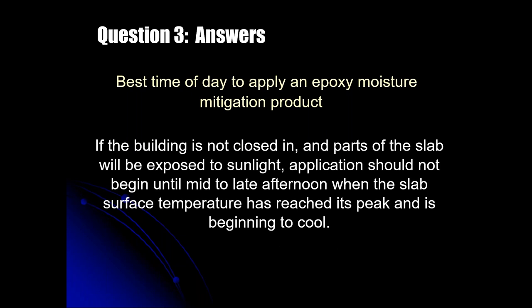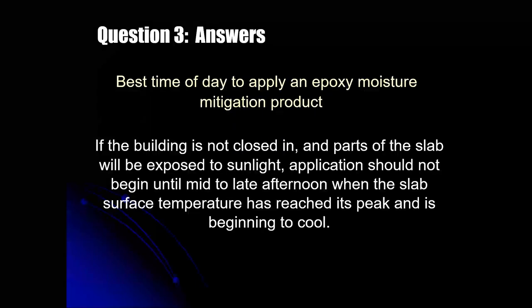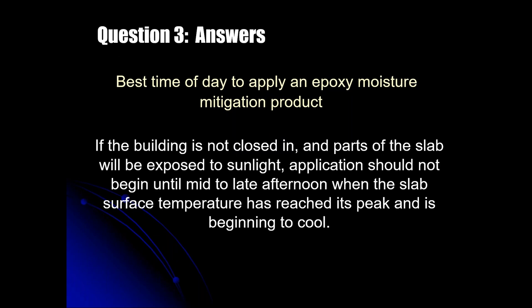What's the best time of day to install a moisture mitigation product? If you're trying to apply any type of coating to concrete in an exterior environment, and I've lived this painfully, the last thing you want to do is apply it in the morning as the deck or the slab is warming by the sunlight. You'll end up having a terrible time with pinholes, as the air in the pores of the surface is expanding and creating pinholes. So ideally, if you're in the open, you want to wait till the slab has reached its maximum temperature, so the air is already expanded and actually beginning to cool.